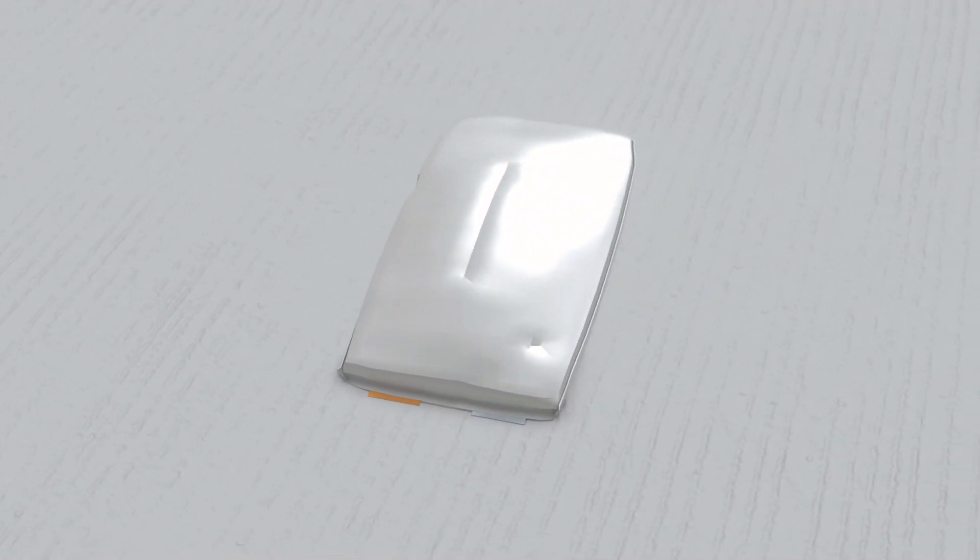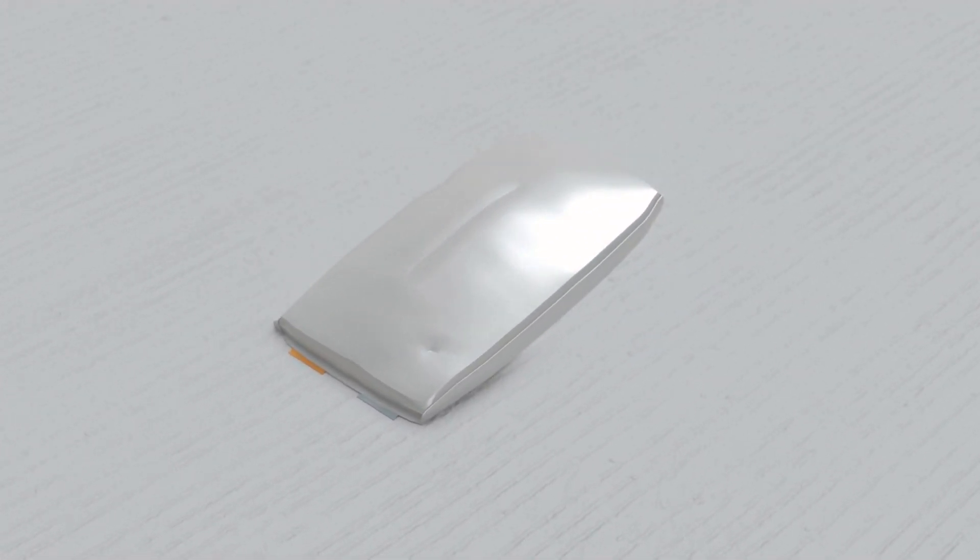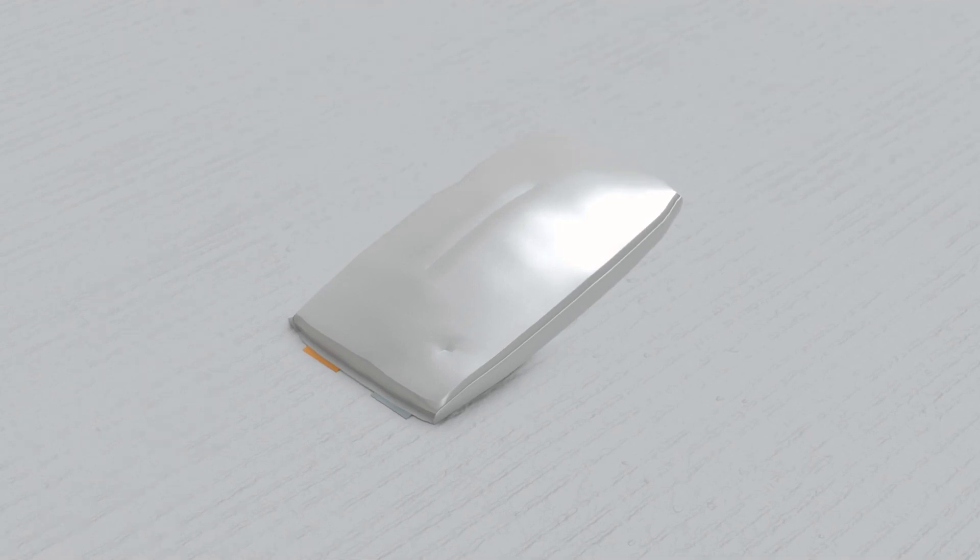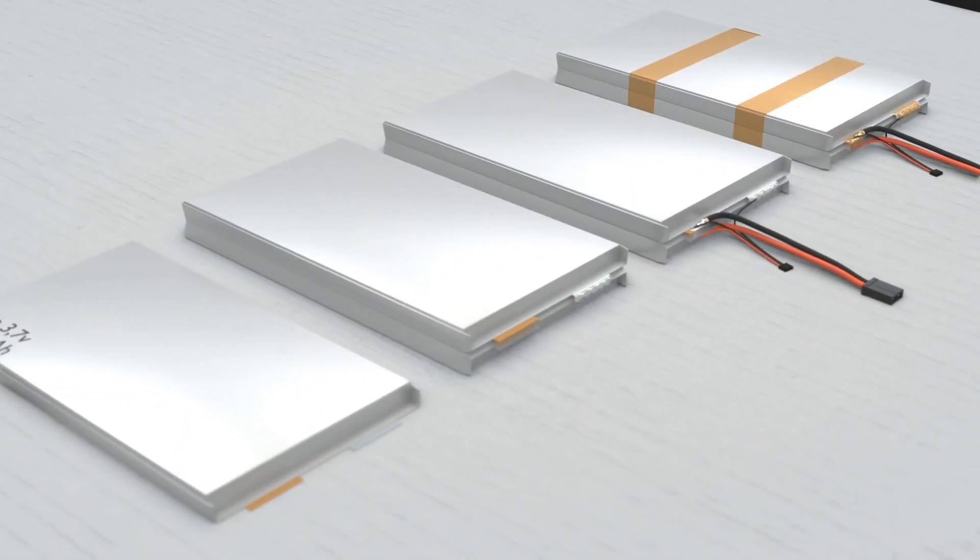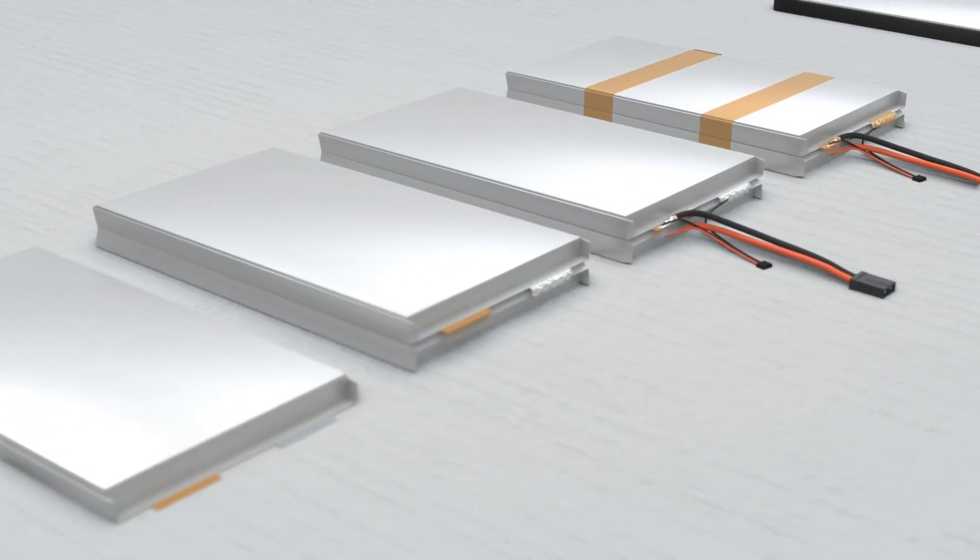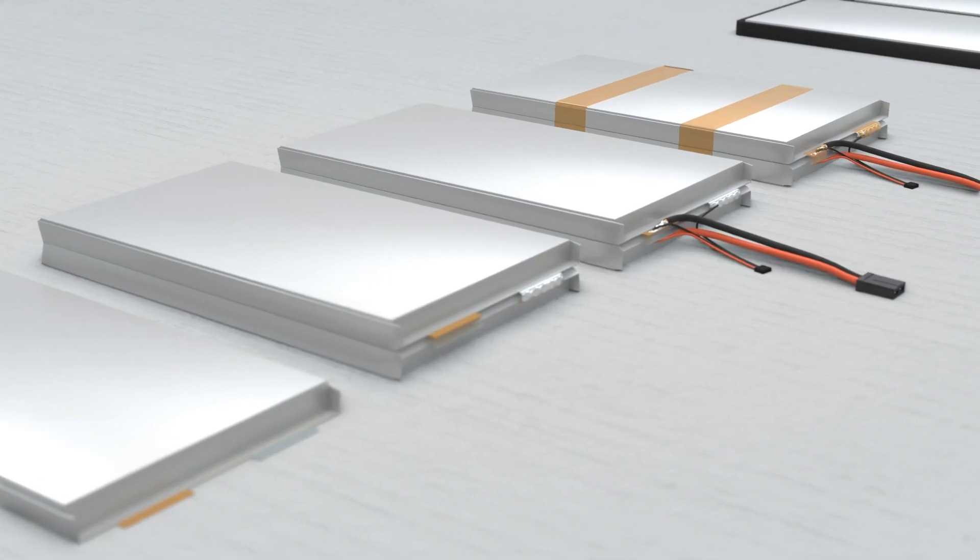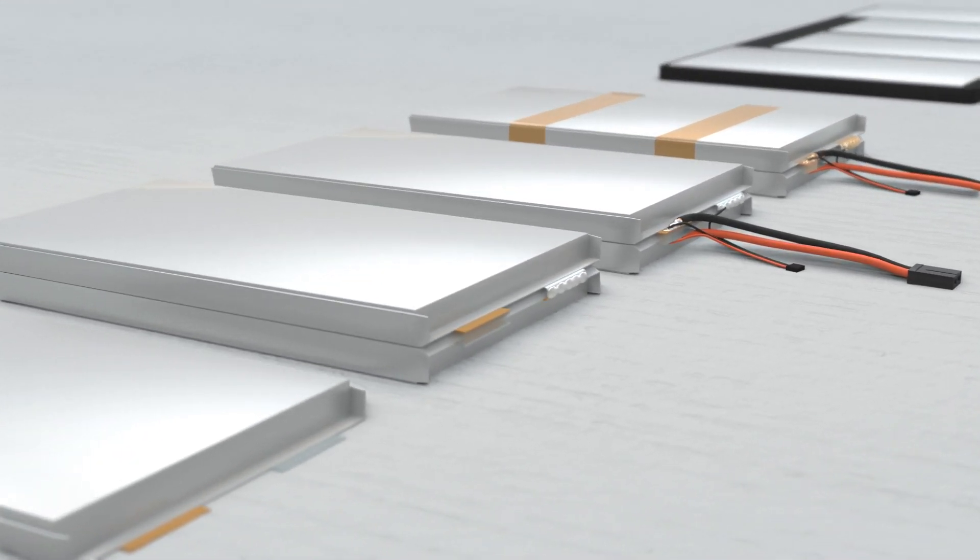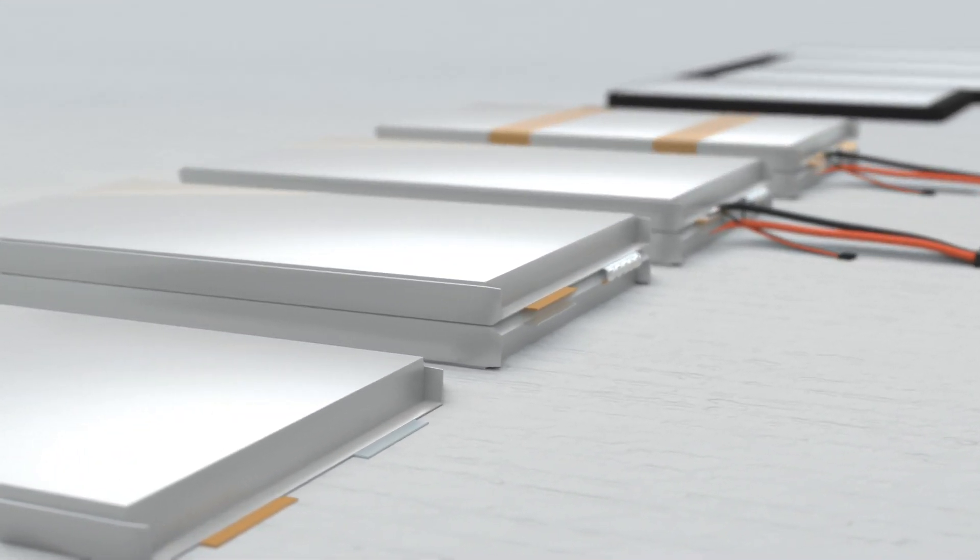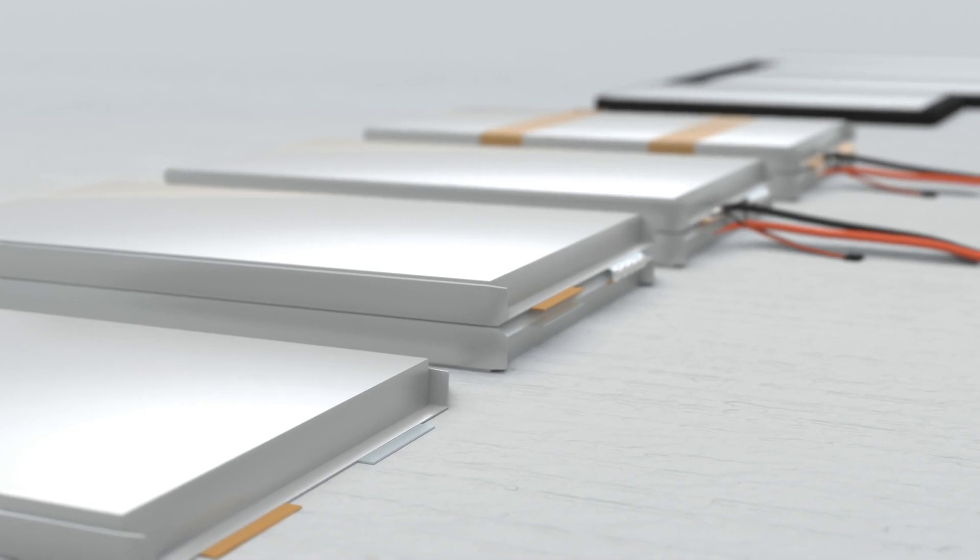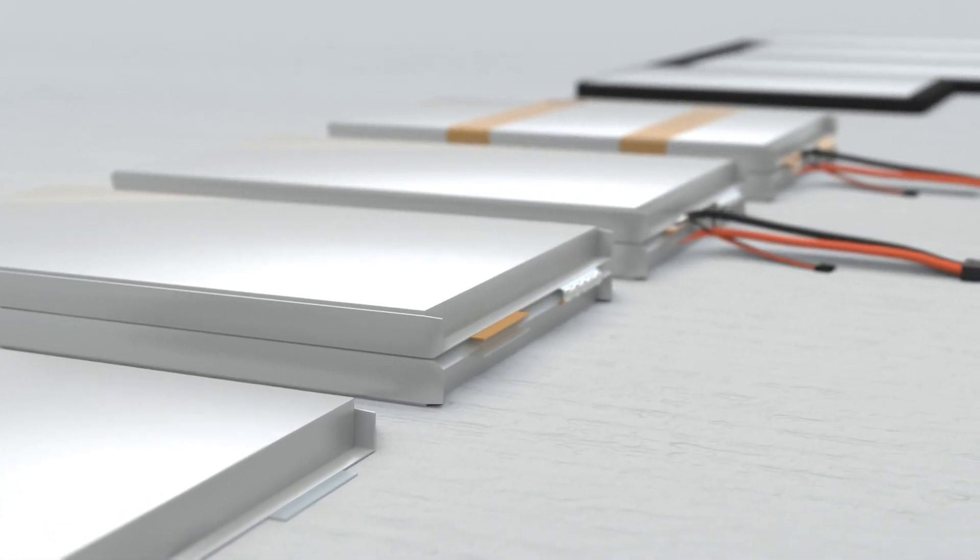Expanding of the cell is a clear sign of damage and it should not be used anymore. There are several reasons why a cell is expanding. This is because of vaporization of the electrolyte, making the pouch expand, that mostly leads to a delamination of the cell.